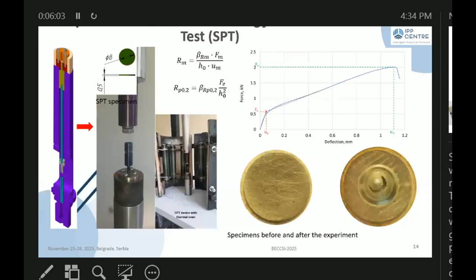And similar to the tensile test, grips with adapters were designed and manufactured for the small punch test. The grip consists of an upper and lower die, between which the specimens were placed, the punch, as well as the grip bushing. Here you can also see one of the test graphs and a specimen before and after the experiments.